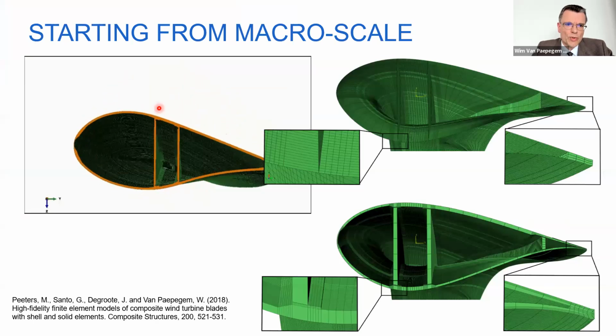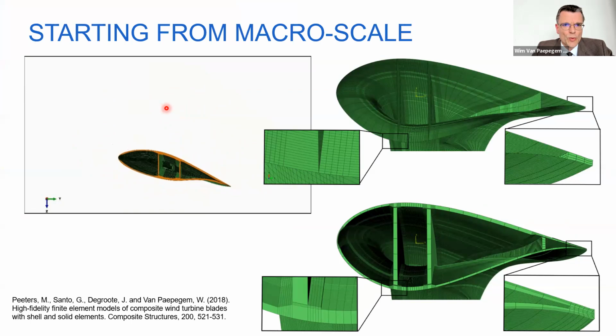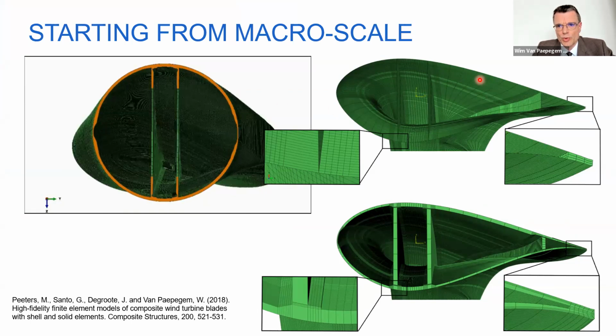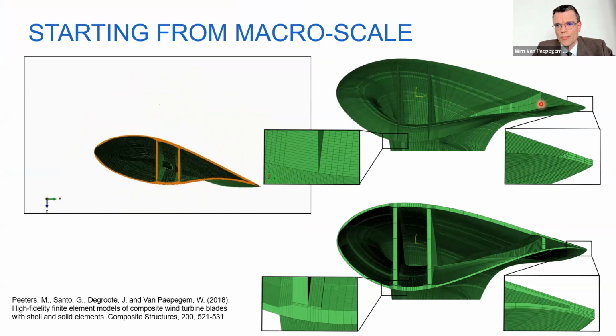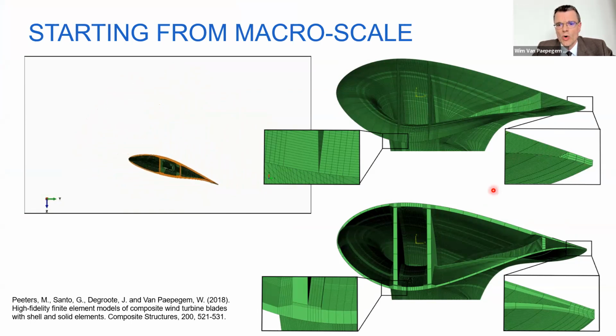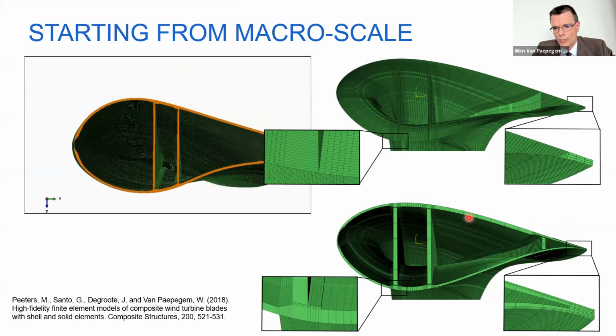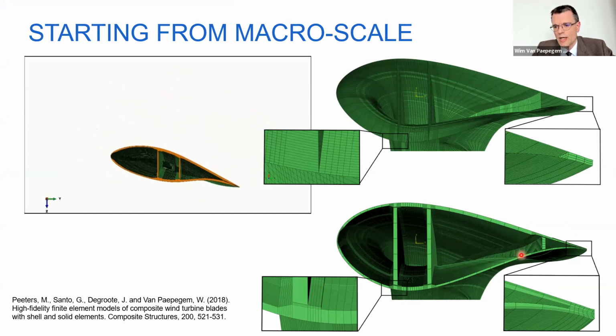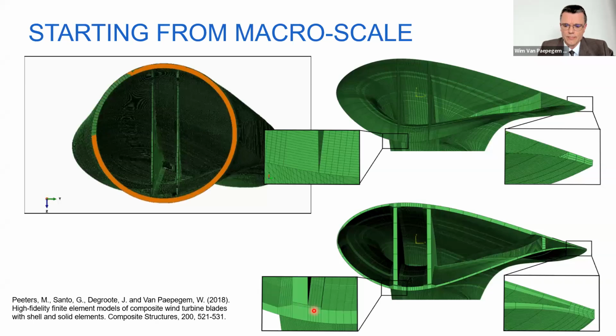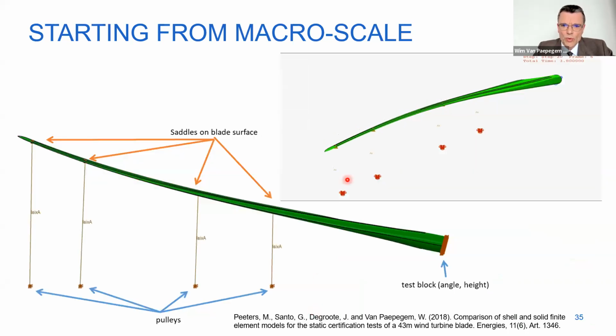For quite some years already, we have worked on developing meshing tools for automated model generation for these large blades. We can do that with pure shell elements. So this is a complete shell element mesh, except for the adhesive joint here. Or we can have a full solid mesh where the whole blade is meshed in solid elements. These are then multi-layer elements describing the stacking sequence. And you see in detail the adhesive joint and also the connections of the shear webs to the airfoils. All very nice, and we can do the same certification test that I just showed you before. So we have some winches that pull the blade to the ground, and we can simulate that behavior.